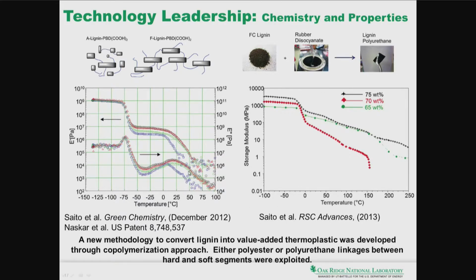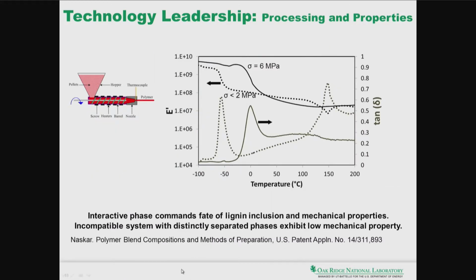Based on this background, we learned that lignin can be modified to value-added thermoplastic by a copolymerization approach. Now, our current approach is, can we demonstrate that using a reactive processing technique? In this case, of course, we used an extruder to modify this lignin. On the screen, you would see dynamic mechanical analysis data. The dotted line shows a rubber phase blended with lignin, and you can see the identity of rubber phase and lignin phase are clearly visible there. The lignin has a softening point near 150 degrees Celsius, and rubber has a softening point below minus 50 degrees Celsius.